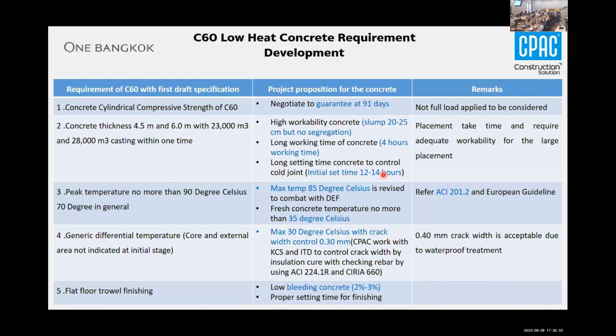This is a table that summarizes what we discussed about the concrete properties for the project. First of all, as I mentioned, we talked about C60 for the mat foundation, but in general, we have to use high volume fly ash. So in general we guarantee the compressive strength at 28 days, but for this one, to achieve C60 at 28 days, I think it's impossible. So we talked about a 91 days guarantee of the strength from the concrete supplier. This doesn't matter for the construction sequence because the concrete develops strength, and once 28 days is around 60%, workers can continue their job. There is no effect from this.